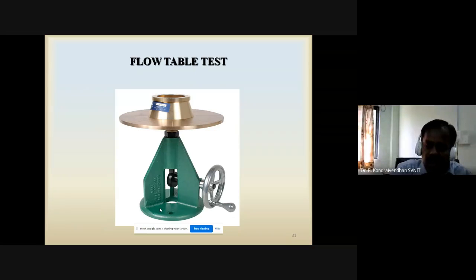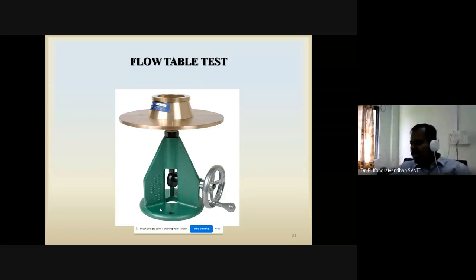Okay, so then for a flow table test, you want to use it for the cement mortar according to IS 1727. You prepare the cement mortar and place it in 3 layers, and give 10 blows in 6 seconds. Then you measure the spread in diameter. From the spread in diameter, 110 plus or minus 10, you have to get it. That's how we get the optimum dosage.